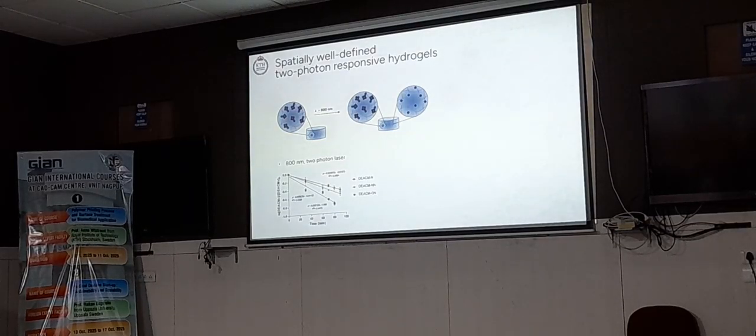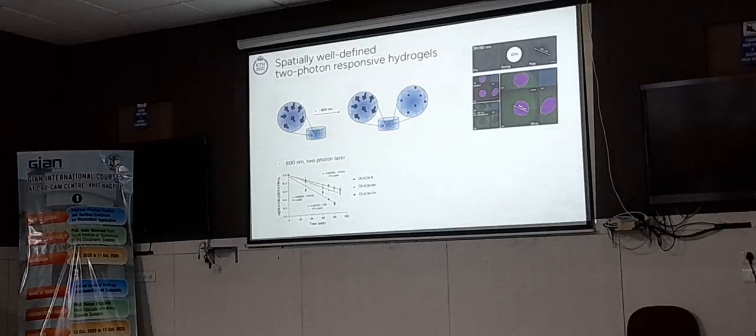Right? So we tested that. It's a quite small picture perhaps, but what we did was that we irradiated on a region of interest, and we could see that in this region of interest the fluorescence was less. We could also see that if we added a dye, this dye was attached exactly onto where we had irradiated.